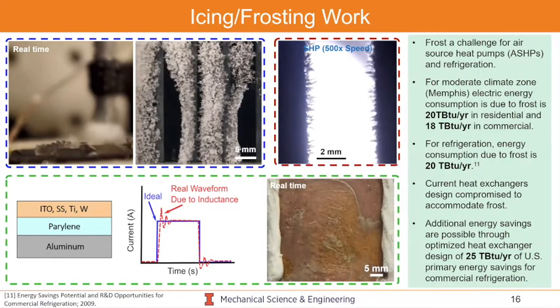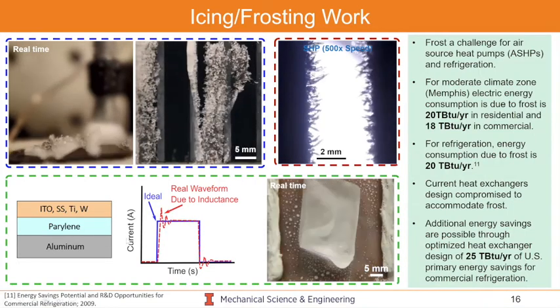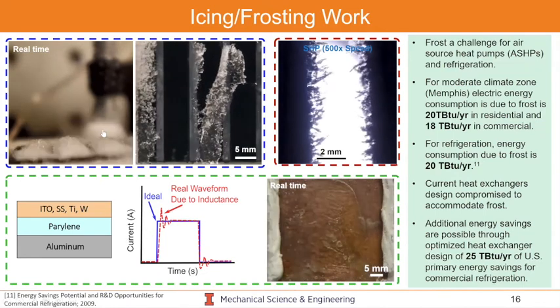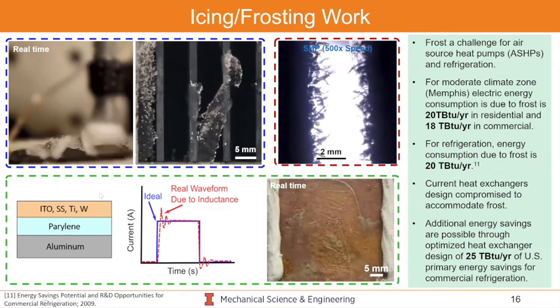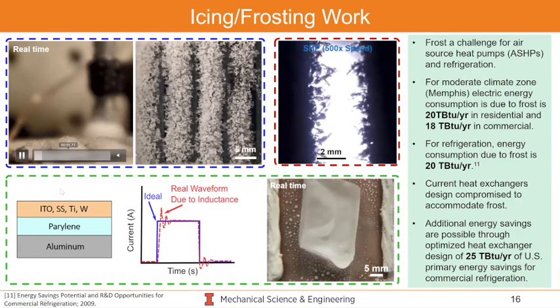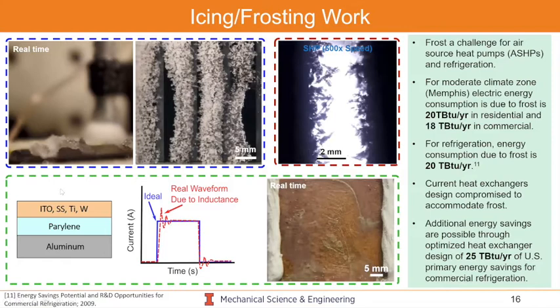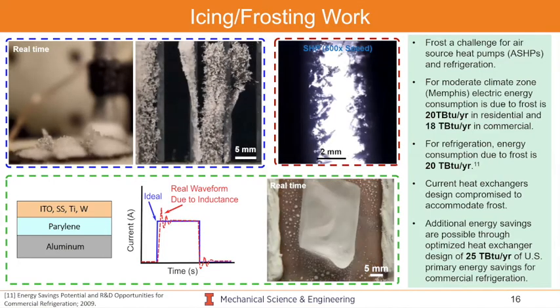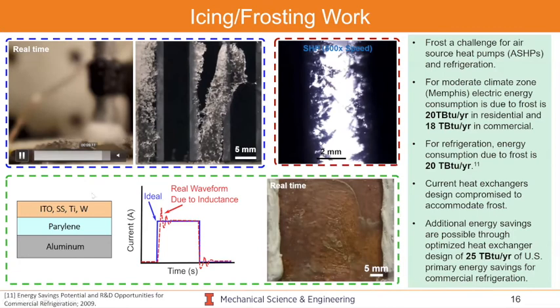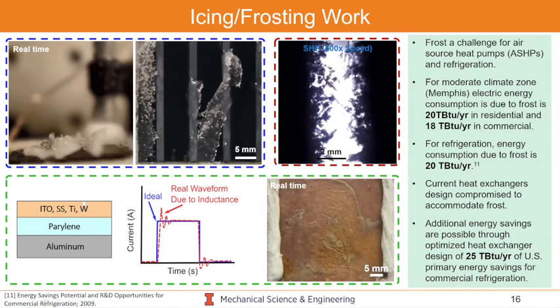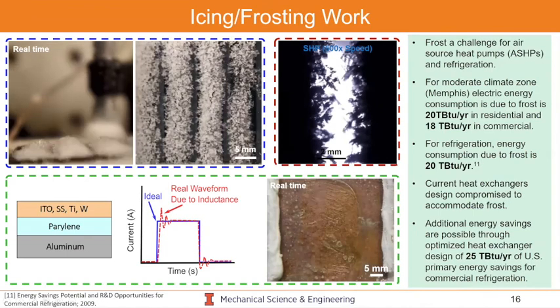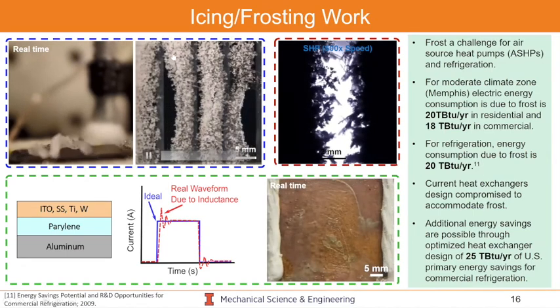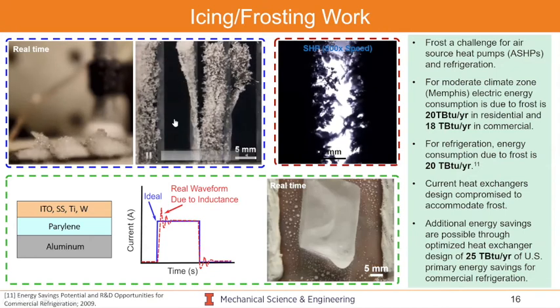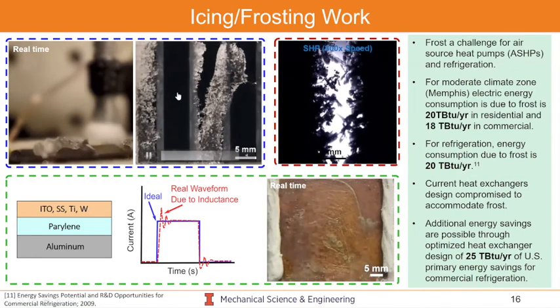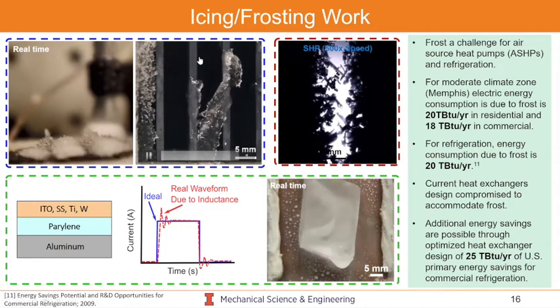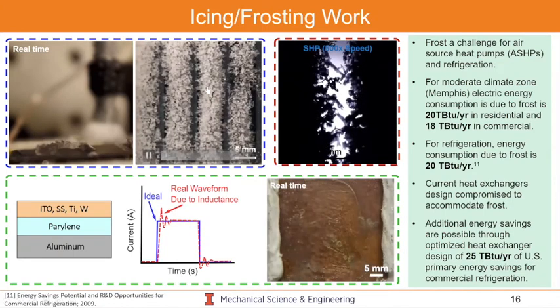So this gives you a few of the different approaches of anti-icing work that we do within the lab. On the top left here, what you're seeing is a physical process we call deblooming. In the regions where frost is coming off, those are superhydrophobic, and these basal regions here are superhydrophilic. As the frost melts, it'll want to melt into the regions of high wetting. Like you're seeing here, the black regions are non-wetting, and these gray regions are wetting, and you can see the frost will debloom or come into these wetting regions and really enhance the efficiency of your de-icing process.